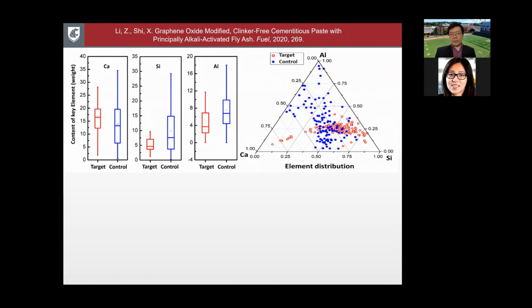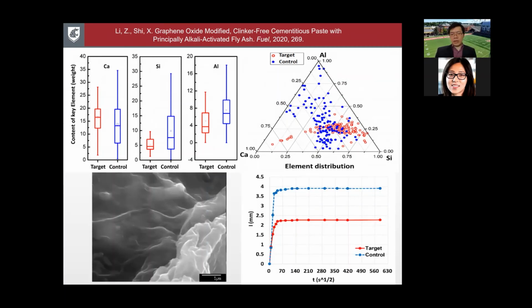So one interesting thing is on the left-hand side, you can see the formation of certain layered structured hydrates. They're actually not your graphene oxide because graphene oxide is much finer. But that basically tells us the hydration process benefits from the template effect of the nanoplatelets. So the graphene oxide nanoplatelets guided or coached the formation of fly ash hydrates.